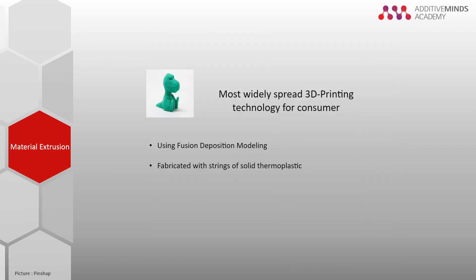FDM is a relatively cost-efficient manufacturing method and quick to iterate. Different materials can be combined to achieve desirable mechanical properties. However, it is vital to consider using support structures for angles typically lower than 45 degrees. Because of the rapid cooling rate, the connection from one layer to another is not as strong, and therefore the mechanical properties are not fully isotropic.